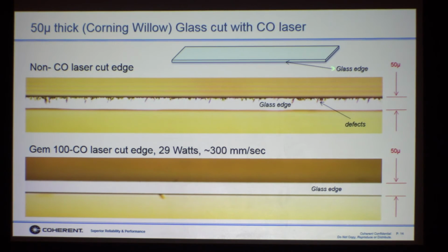And so I have a little cartoon here. This is the edge of the glass. This white part is the edge of the glass, and the yellow is the outside. So this white part you can see is the way the glass was delivered to us. We don't know how it was cut. It was either cut mechanically with a diamond wheel, or it was cut with a CO2 laser or a picosecond laser. I have no idea. All we know is that whatever they used for the cutting process created a lot of defects in here, okay?